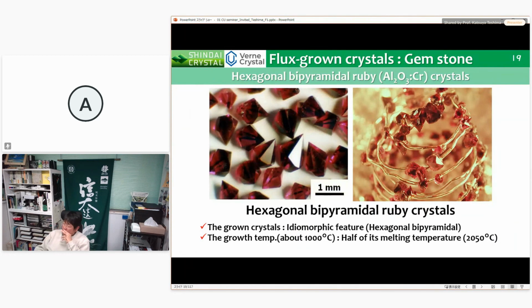In this case, the growth temperature is about 1000 degrees C, which is about half of its melting temperature. The melting point of the alumina material is about 2050 degrees C, so it's about half of its melting temperature.